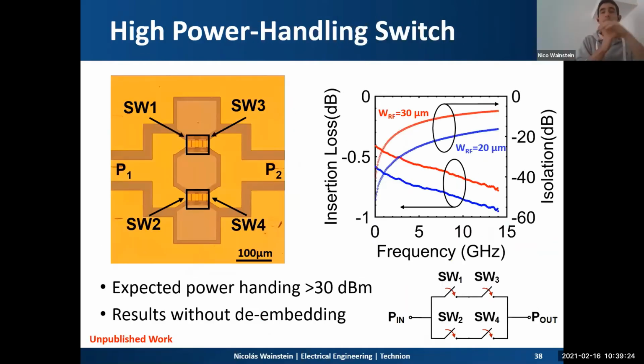And so to overcome this power handling issue, we used a series-parallel configuration scheme where two devices are connected in series and in parallel with two other devices. This way, the on resistance and the off capacitance theoretically remain low, almost equal to the single series device. Also, the voltage drop at each device will be smaller because of the configuration, and therefore we prevent the voltage from rising above the threshold voltage, causing an undesired phase transition.